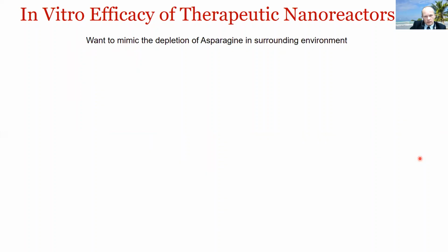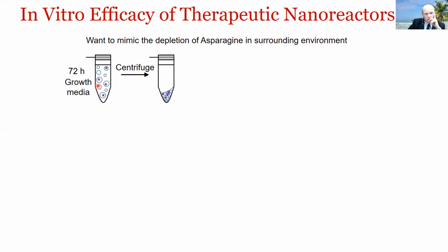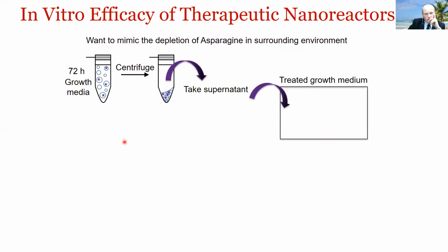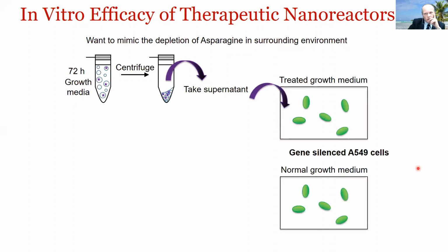So we tried to mimic the depletion of asparagine in the surrounding environment, which is what happens, as I said, in a leukemia. So the way we did this was to assess the ability of our polymersomes to inhibit cell proliferation in vitro. So we generated cells that were deficient in ASNS to simulate leukemia, and then A549 cells were gene silenced with the appropriate siRNA, making them dependent on an external asparagine to proliferate. So we took our ASNase vesicles in growth media to provide us with a depleted environment, centrifuged to remove the vesicles, and then took the media and used this supernatant as our reduced asparagine environment, and then used that treated growth media with our gene silenced cells and with the normal growth media.